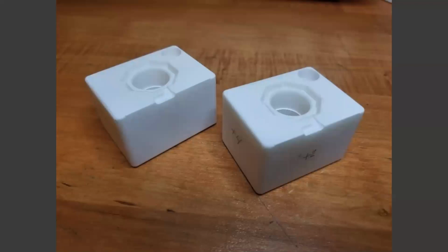Thank you, Juliet. Here's a sample of our inspection point. So when our block's printed, you can see there on the screen, the +2, the +4, that's written in thousandths of an inch. So we were material heavy in the Y direction, +2 thousandths. And when miking over the length of the block, we were +4 thousandths. So there is a little bit of variation. Again, that was done early in the 10K resin's test phase. So during beta, those were numbers that Formlabs was working on improving accuracy of print. But that's something that we watch closely because we know if we flash the mold, it's going to be problematic. We won't be able to demold quickly, and then we risk breaking the part trying to get the plastic part out of it.